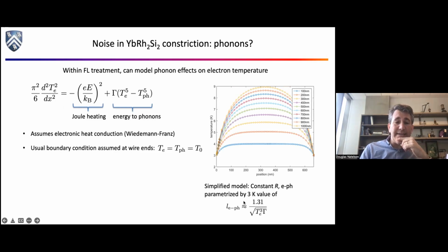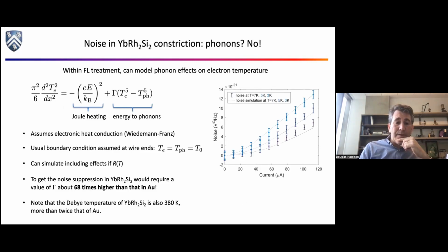And the bottom line is, if you want to get the noise squished this much, you have to assume that this gamma is 68 times higher in ytterbium rhodium 2 silicon 2 than in gold. And there is zero evidence in other measurements for that at all. If anything, you actually expect phonons to matter less in ytterbium rhodium 2 silicon 2.